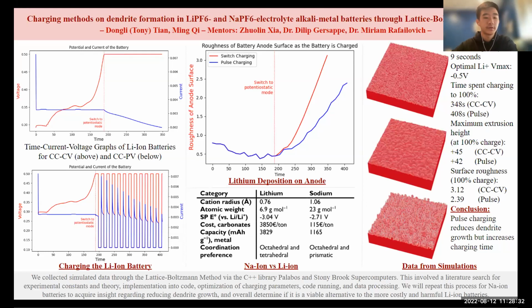We simulated a lithium half cell using lattice-Boltzmann methods in the Palabos library in C++, and with the Stony Brook Seawolf supercomputer, then simulated charging that battery using both methods. Our qualitative analysis of dendrite formation was done using ParaView, and quantitative data was processed using Python.